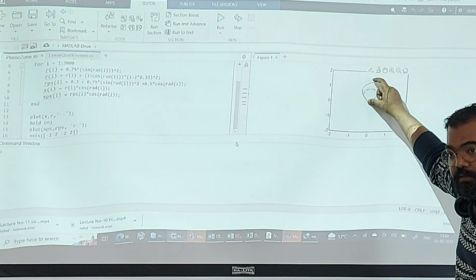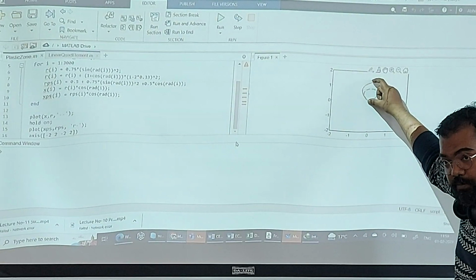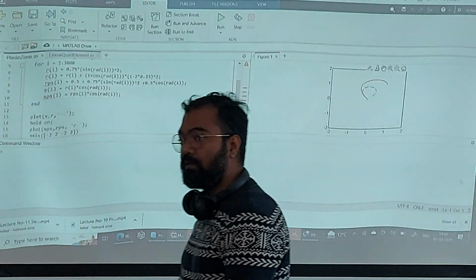So for plane stress condition you have larger plasticity. What does that mean? A softer material. It feels like the same alloy, but if the thickness is less, it acts softer. Why is it happening? Same alloy, same material को change नहीं किया. एक पतला है, एक मोटा है. No magic is happening, just because of the calculation. And in that calculation, nowhere I have assumed anything but plane stress and plane strain. What does that mean? Sigma z in one case is 0 and in another case it is not. What is sigma z? It's the stress in the direction of thickness.